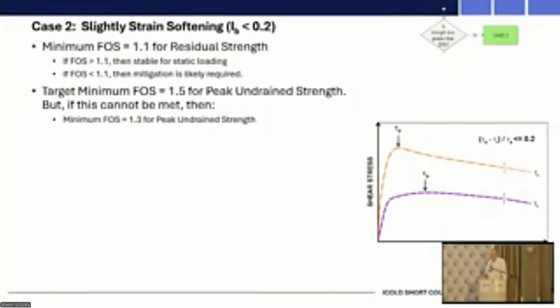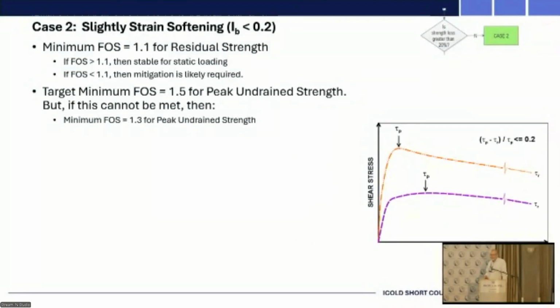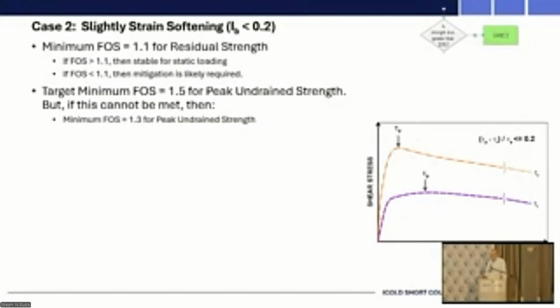Okay, case 2, I'm going to have to walk through this one. It will take a little time because I need to walk through the math. So this is a case where you have strain softening with a brittleness index less than 0.2. So if you remember that brittleness chart, that's the green area or the upper area that is less than 20% strength loss at 20% strain. And so here the minimum factor of safety of 1.1 for residual strength is very important. If your factor of safety is greater than 1.1 and you have an appropriately conservative characterization, then the facility is stable. If it's less than 1.1, then you likely will need some form of mitigation.